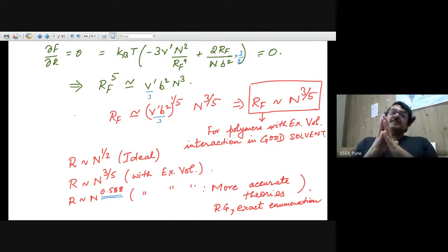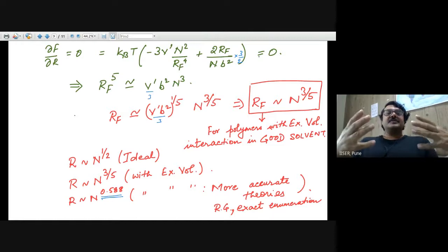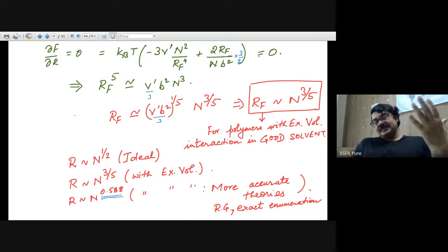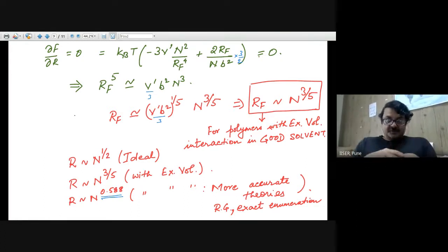But now just consider the pervaded volume, which is r cubed. The radius was 4 times bigger. The pervaded volume is 64 times bigger. And that is just talking about a normal polymer chain with 1 million monomers. So it has actually increased in size 64 times. So basically, something which we would call a dilute polymer chain is now semi-dilute, and that would lead to serious consequences in terms of the properties or the dynamics of the polymer solution, which we have not come to yet, right?